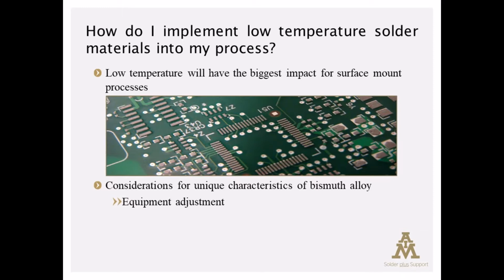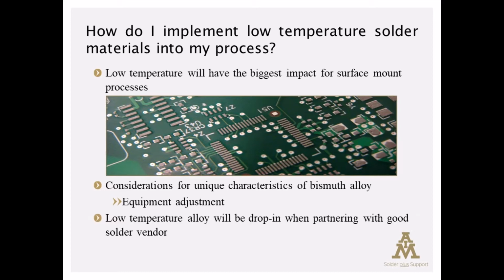But the advantages to a wave soldering process are considerably less than the advantages in a surface mount process, because the main driver here is reduced component warpage, reduced substrate warpage. Going to a low temperature material in wave could reduce your energy costs. So I'm sure that's why people will investigate it for those applications. But by and large, it's a drop-in. You could conceivably start testing it today with the existing materials and learn some of the tricks that are going to be required for trouble-free implementation. But I'm fairly confident with a good solder vendor partnering with you to help you understand what those problems are and what the solutions may be, this could be a very successful endeavor and yield positive outcomes.